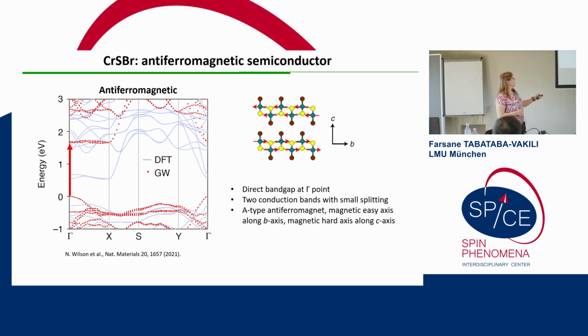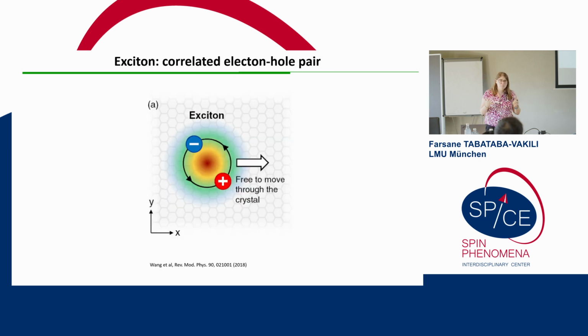Then it's a layered A-type antiferromagnet. So the monolayer is ferromagnetic with the magnetic moment along the in-plane b axis, and then the interlayer coupling is antiferromagnetic. We have a magnetic easy axis along the b axis and a magnetic hard axis along the out-of-plane c axis. So since this is a workshop about magnetism, I thought I would introduce this guy to you.